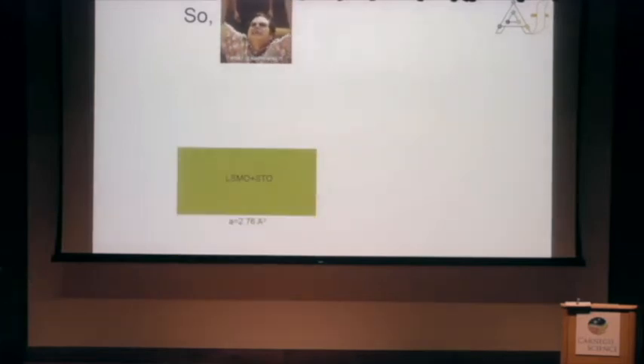Okay, so what is happening, right? We do have LSMO STO. Here I'll show a very hand-waving cartoon. I will select an in-plane parameter, which is convenient for me. So this is the 110 in-plane parameter of the LSMO STO, on which we grow a T phase. Initially, a T phase is formed for 2 to 3 monolayers, after which the system wants to relax strain.